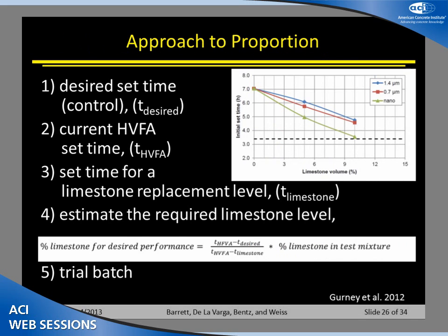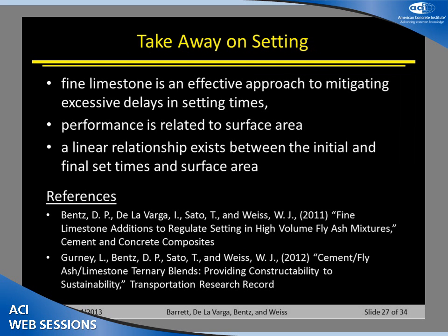A procedure's been developed where you can run through a series of calculations and figure out how much limestone you would need to get back to an equivalent set, or whatever set time you would need. If you're interested in this, we can provide you the paper that gives a lot more details on this. So fine limestone is really an effective approach to mitigate some of these excessive delays that occur when you're using higher volume ashes. The performance is completely related to the particle size or the surface area.